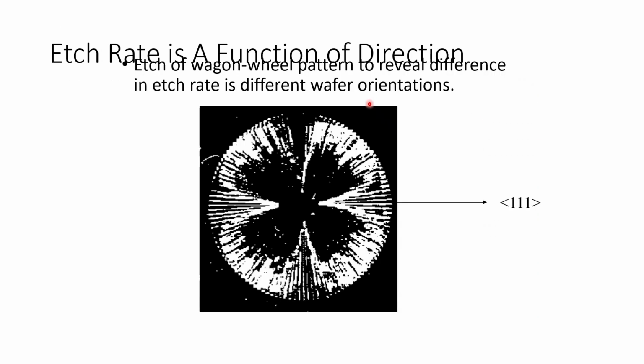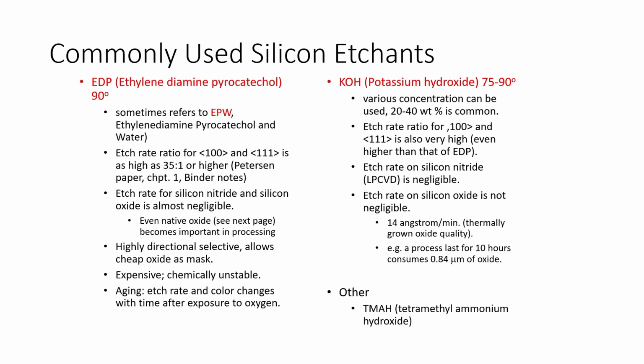The etch rate is different in different orientations. In the 111 direction, the etch rate is the slowest. This is a wagon wheel structure that demonstrates the etch rate differences in different orientations. 111 is the slowest. As I mentioned, you can use EDP or KOH.